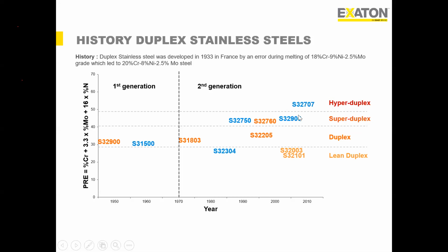This hyper duplex is quite a new material. I think it has been developed over the last decade or less. So far, this particular grade was developed by Sandvik, a Swedish steelmaker, and recently we got the UNS number. It's called UNS 32707. So this chart shows that hyper duplex has the highest PREN value, so it has the highest pitting resistance compared to super duplex, duplex or lean duplex. Super duplex is inferior in terms of pitting corrosion compared to hyper duplex, but it is superior to lean duplex and duplex. Duplex is inferior to hyper duplex or super duplex, but it is superior to lean duplex, and definitely lean duplex is the lowest grade among the duplex family.